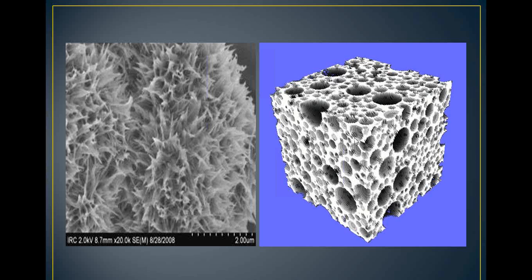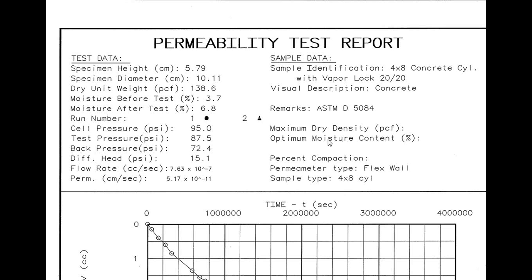Making more of this, filling in more of these holes. On all of our warranted projects, we send out cylinders taken from the concrete truck at the time of placement to an independent lab where they conduct this test, and we send them a 4-inch diameter by 8-inch cylinder, and they slice a 2-inch hockey puck out of the center of it, and they push water through it. And in this particular test, these were the results: 5.17 times 10 to the minus 11th centimeters per second.